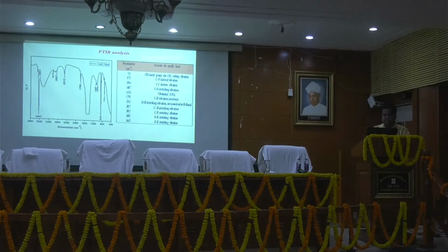Now for the FTIR analysis, for our calculation of bonds, meaning what kind of bonds our calcium oxide nanoparticle has. So you can see different peaks are there, like at 713, which indicates a CH3 methyl group. For 873, it is carbon oxygen skeleton vibration. So different types of peaks are present here in our sample, which come from the presence of calcium oxide nanoparticle.